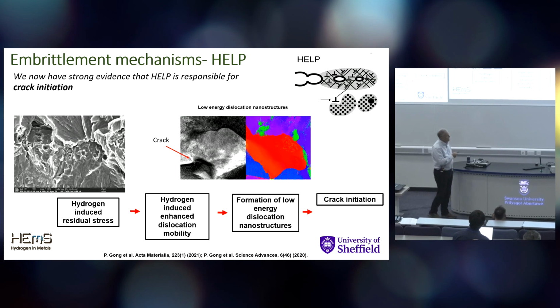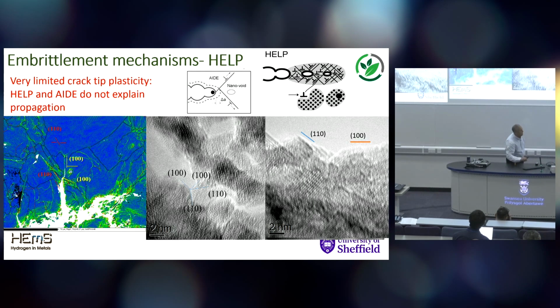So it sort of agrees with the HELP mechanism. Some slight differences, we don't get this sort of voiding and that sort of thing taking place, but it is consistent with those observations of crack initiation. But the crack propagation is really quite different.